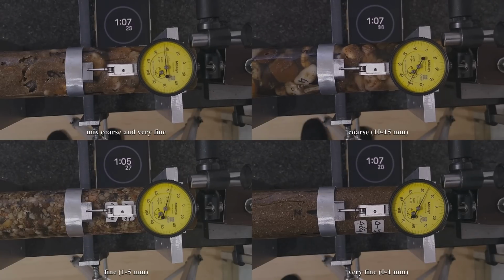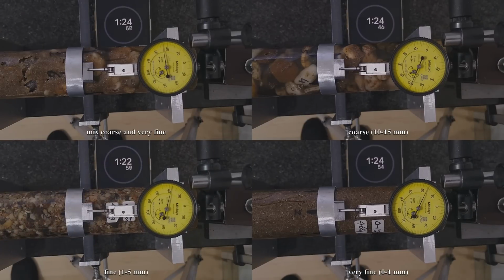After 2 minutes, very fine is still in the lead at 35 microns, but closely followed by fine at 38 microns. The mix has bent further to 48, and the coarse epoxy concrete has dropped all the way to 110 microns.